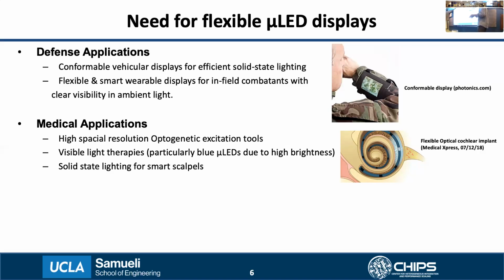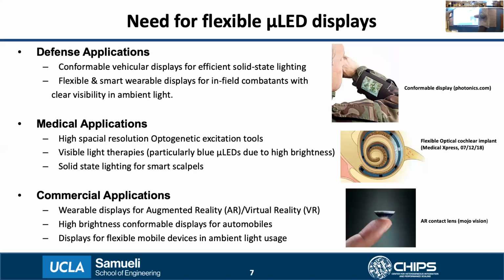For example, in the image on the right, you see a micro LED display used as a cochlear implant for doing the optogenetic stimulation. The third application is the commercial sector, and in the commercial sector, the need for micro LEDs is mainly in wearable displays for augmented reality, virtual reality. Because in this particular application space, again, you need a display that can have a very high refresh rate because of the data rates of current video, and also you need a display that is very bright, so you can even see the images when you are in ambient lighting conditions. There's also a need for flexible micro LED displays for automobile head-up displays. So what all these three application spaces have in common is that you need a display that is very bright, can work in ambient lighting conditions, and can conform to any curvilinear surface.